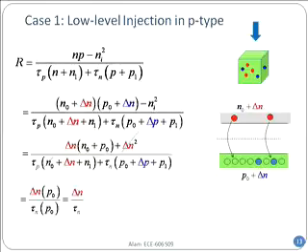So the few electrons you have pumped up in the conduction band, they see a sea of holes all around them because it's a p-type. And they bump into the holes all the time through the traps and keep recombining. So therefore, you don't see anything related to the holes in the expression here. You see, there is delta n over tau n. Because holes are so numerous, anytime it wants a hole, it will get a hole. So as a result, I do not have anything in the final expression related to the holes. You see, that's not a rate limiting supply. You have to understand the meaning of the equation so that you remember it exactly.